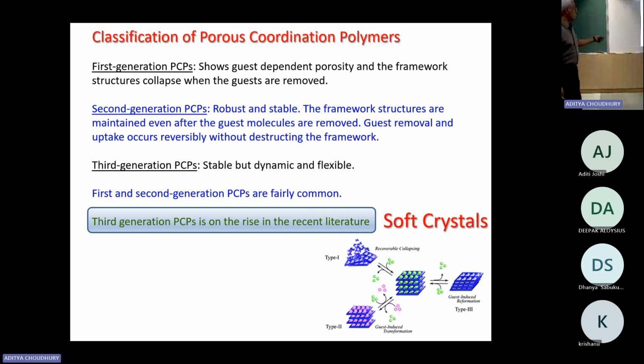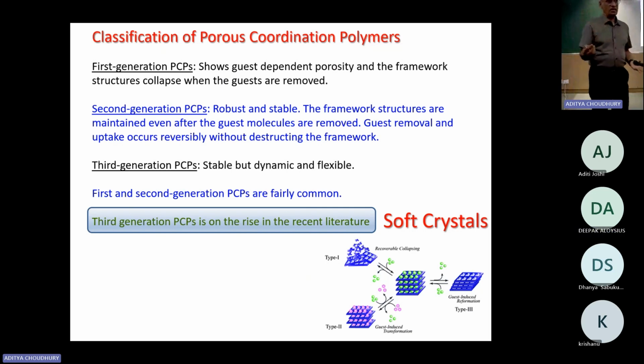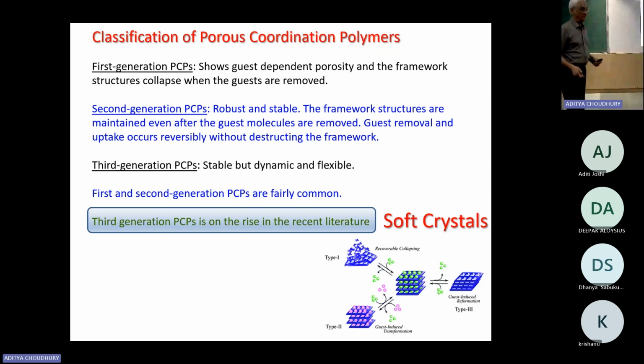The reason is all these porous coordination polymers have solvent. Once you remove the solvent, what happens to it? In the case of first generation, once you remove the solvent, the whole framework collapses. It is not just single crystal. Of course, you have single crystal, and if you remove the solvent, the single crystal collapses. And also, if you record the powder pattern, the same powder pattern that you simulate from the single crystal is not retained. It's amorphous. So you know that something happened to it. Completely, it is destroyed. Okay.